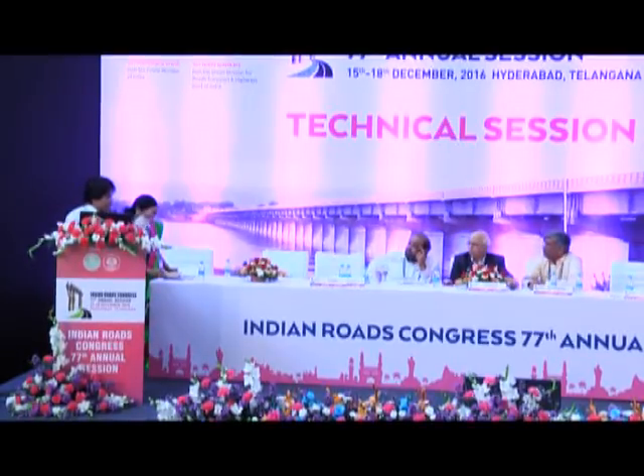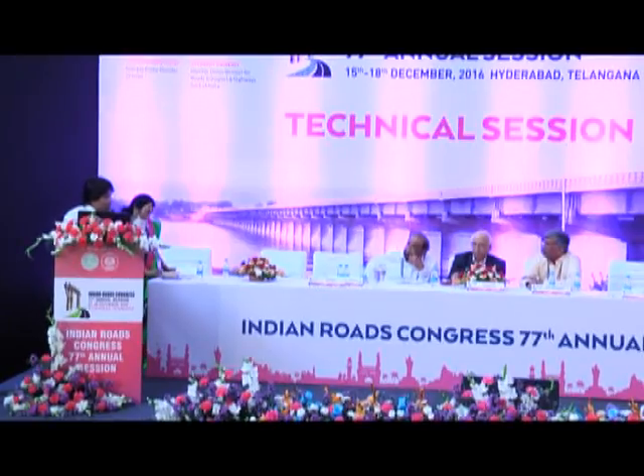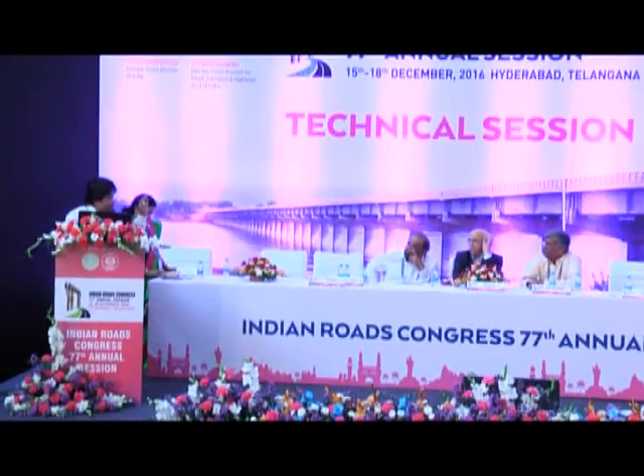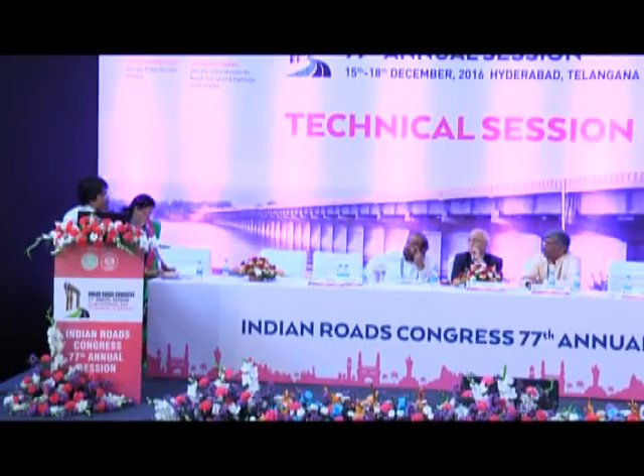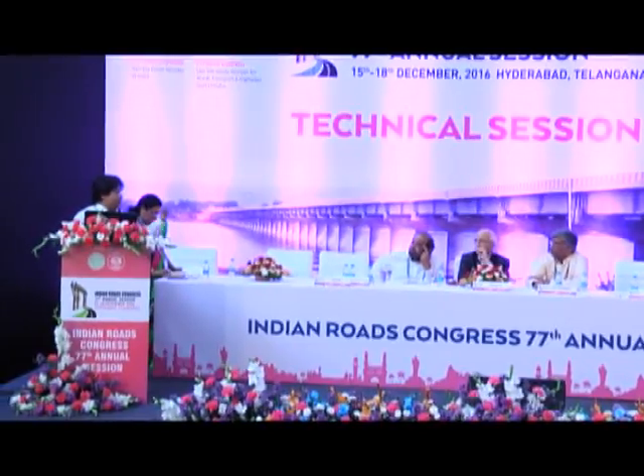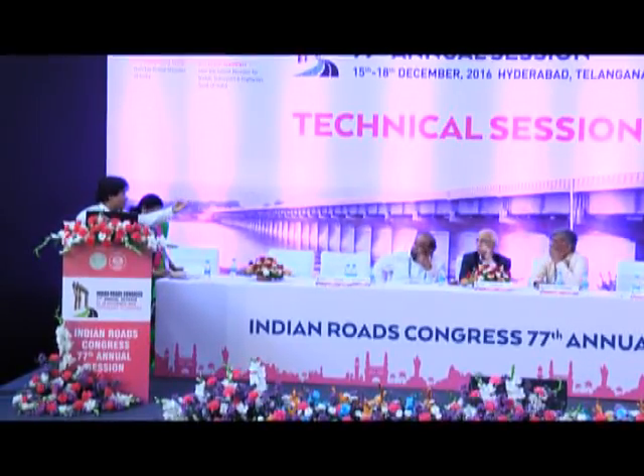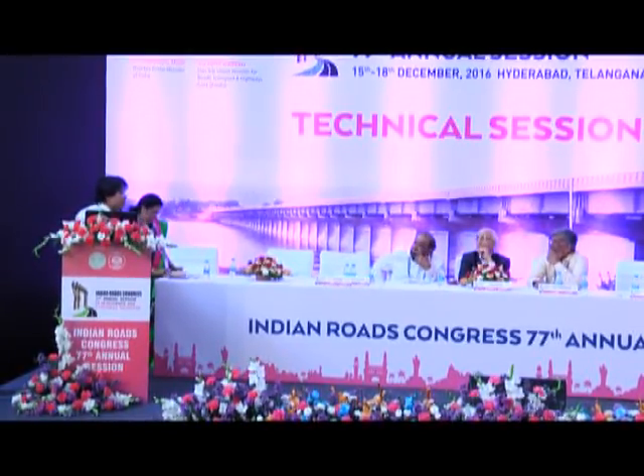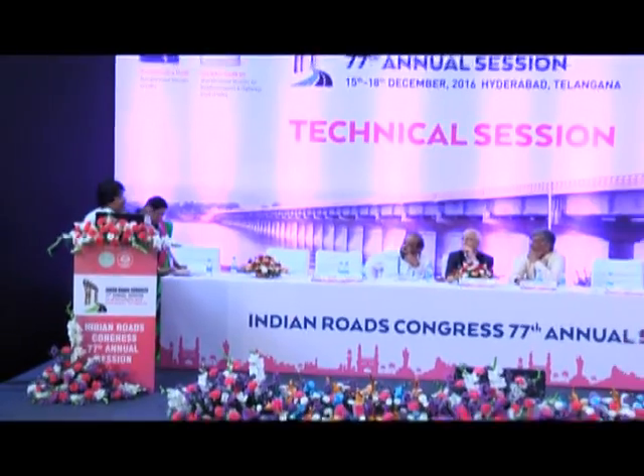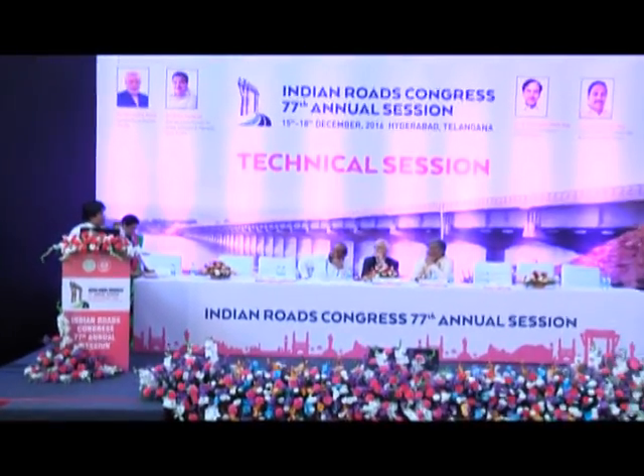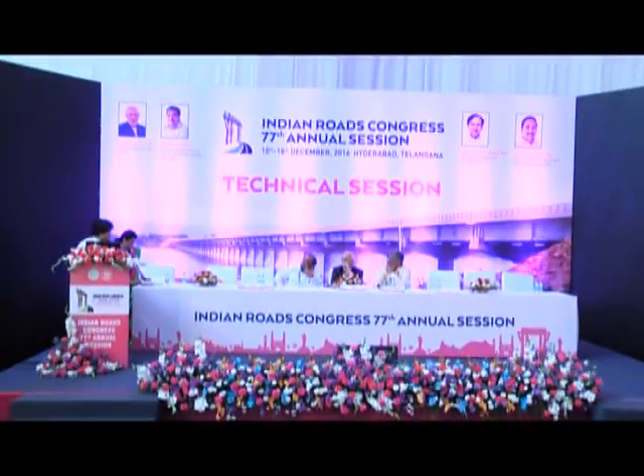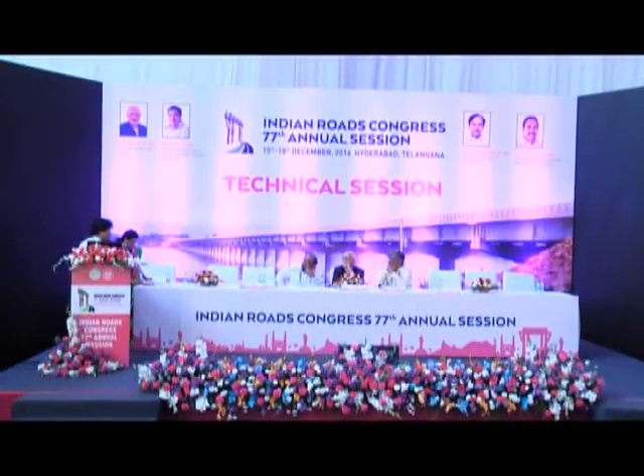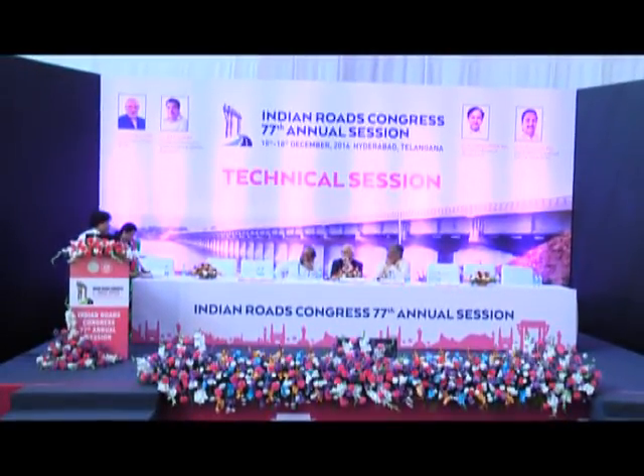The first question, what I understand from you, is that it depends upon the aging factor of the bitumen. Now you reclaim the bituminous course which had been laid just 2 years ago. In that case, it would be very difficult because the bitumen engulfing the aggregate is still in active mode, not yet aged properly.